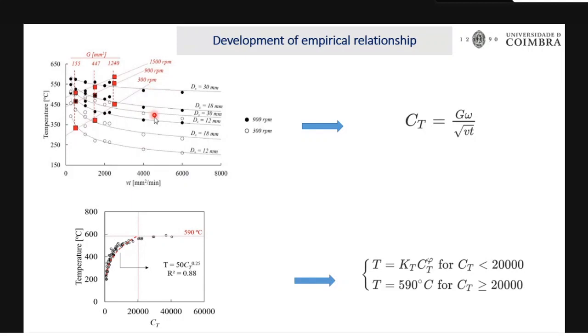First, just consider these curves. I'm going for curve fitting, and this curve fitting is perfectly matched with 1 by root of x, where x is Vt. So here I made 1 by root of Vt. Then I see that as G increases, the temperature increases, which shows that the temperature is directly proportional to G, so I introduce G in the numerator. As the tool rotational speed increases, the temperature increases, so I use omega in the numerator as well. In this way, the coefficient of the temperature is predicted.